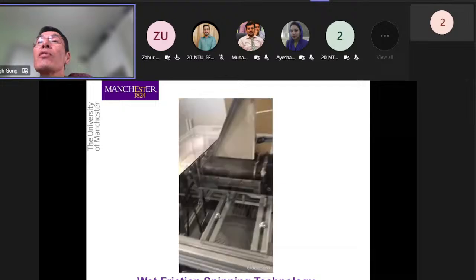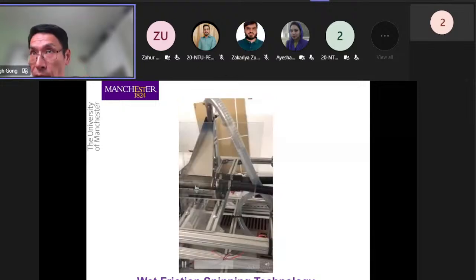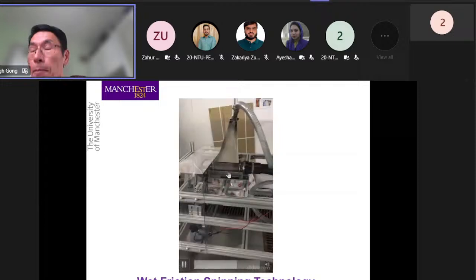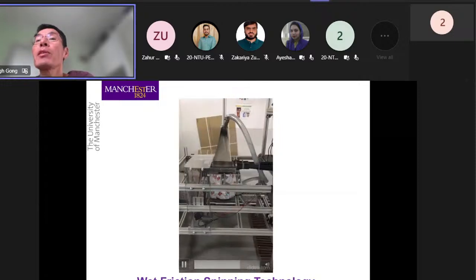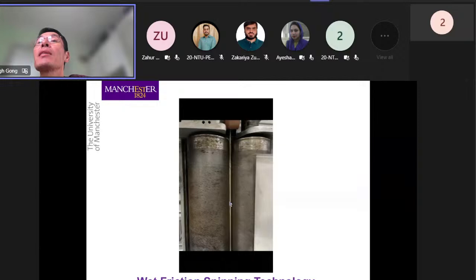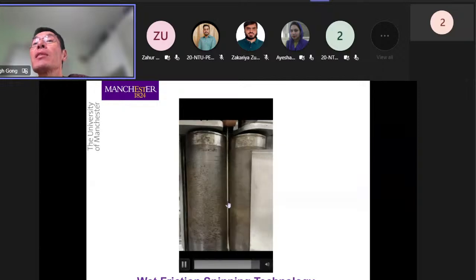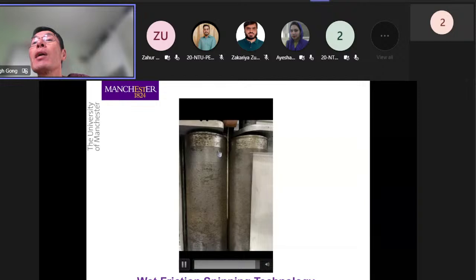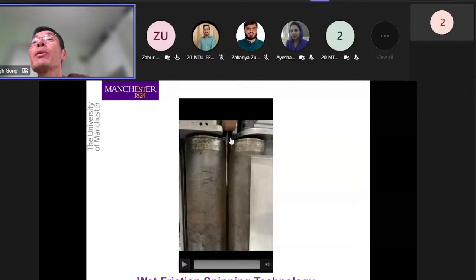So that's the friction drums there, and you can see a lot of duct material for transferring the fibers in solution, and then you of course have a winder to take up the yarn. So that's the essence. So this is the spinning zone where the carbon fibers will be wrapped around a core. Again, we had to use a core fiber in order to get the yarn out. So it's not a purely recycled carbon fiber yarn. It's a sort of composite with a core fiber. Then we have the carbon fibers spun around that.